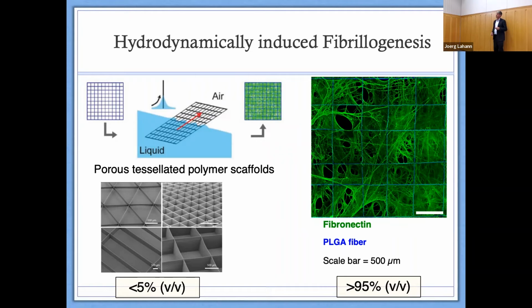What we have done is explore the roughness, this defined tessellated roughness in those structures, to use a shear field to induce fibrillogenesis of a protein, in this case for instance fibronectin, over the entire area of our scaffold. So in the end, you get this fibrillar structure of fibronectin that looks very much like the extracellular matrix proteins that a cell would deposit. That's actually very distinct from just plasma fibronectin that you coat onto a tissue culture petri dish.